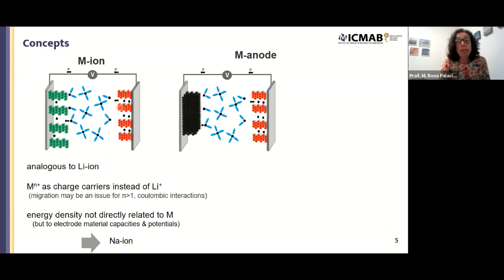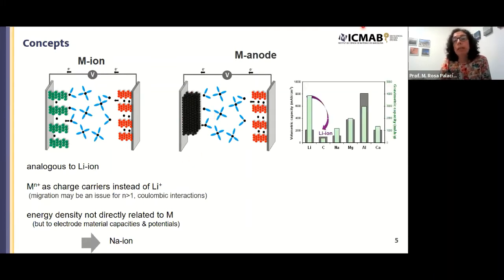And another concept which is interesting is the use of metal anodes. So in this case, the negative electrode would be a metal. And here you can see a graph showing the gravimetric capacity in green for different metals and the volumetric capacity in gray. So you see that gravimetrically nothing compares to lithium metal, because lithium is very light. Of course, when we move from lithium metal to lithium ion, then we use graphite as negative electrode and the capacity is much smaller. And this is due to the fact that lithium metal grows forming dendrites. And this is an issue for the battery safety. But then finally, some metals would be better than graphite if we were able to safely use them.